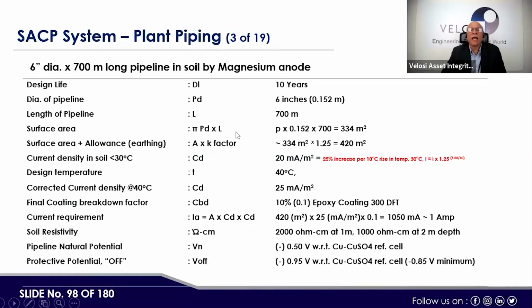Surface area is pi d L. Then surface area allowance for earthing, A into K factor. Then current density in soil, which here is 20 milliampere per meter square, with a 25% increase per 10 degree Celsius rise in temperature. This equation has to be done. Then design temperature 40 degrees Celsius, corrected current density at 40 degrees Celsius, which is 25 milliampere per meter square.